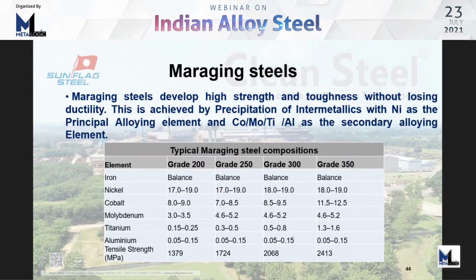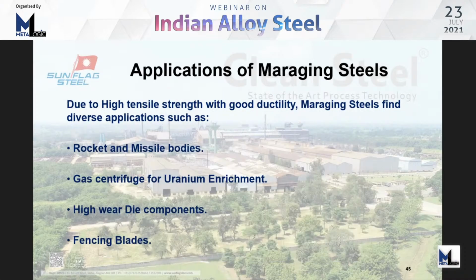Maraging steels develop high strength and toughness without losing ductility. And this is achieved by precipitation of intermetallics with nickel as the principal alloying element and cobalt, moly, titanium, or aluminum as the secondary alloying element. You can notice the tensile strengths. They are 2 to 3 times that of alloy steels. The applications of maraging steels are in rockets and missiles, gas centrifuge for uranium enrichment, high wear die components,